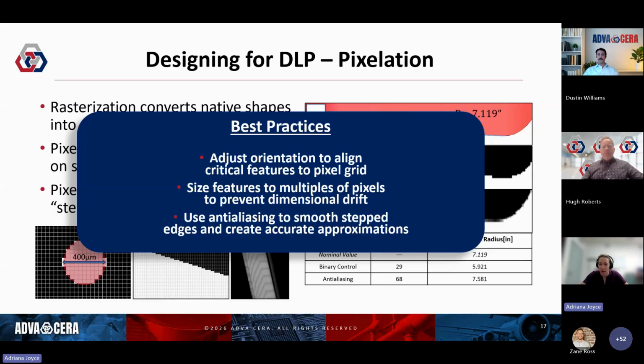It's well established in other additive manufacturing processes, and that adjusts the intensity of individual pixels, giving us a grayscale effect, which lets us make this 7-inch radius curved feature much closer. So nominal is 7.1. Using the binary control, we achieved about 5.9 inches. But with anti-aliasing, we can get much closer, with a 7.5-inch radius on the final part.